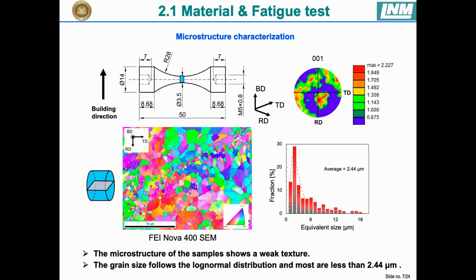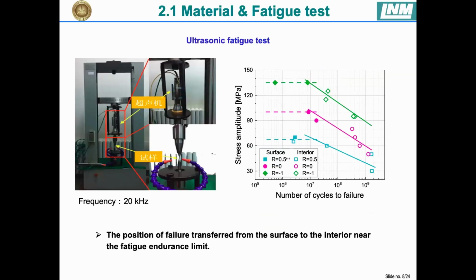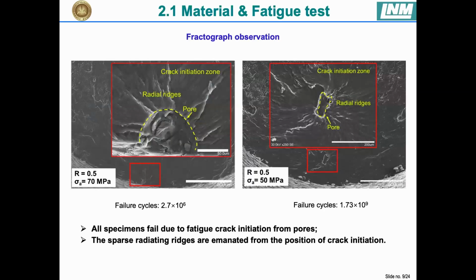Then EBSD is applied to conduct the microstructure characterization. The microstructure shows a weak texture, and the grain size follows a log normal distribution, and most are less than 2.44 micrometers. Specimens are then tested with the ultrasonic fatigue test with a frequency of 20,000 Hertz. The results of the stress and life curves at different stress ratios are plotted here. It can be found that the position of failure transferred from the surface to the interior near the fatigue endurance limit, corresponding to the failure cycle of 10 million cycles.